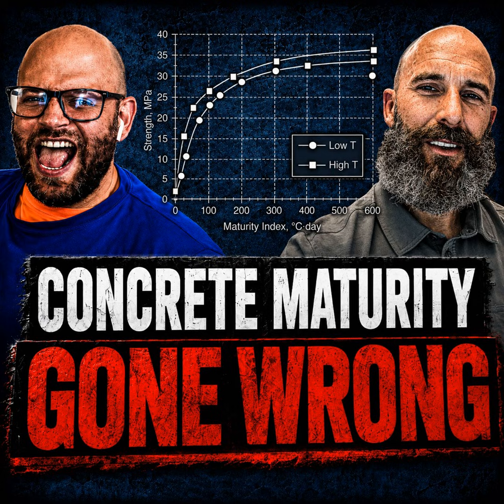So what does datum temperature mean? If I took that type 1 cement to a type 3, it's a faster setting cement. My datum temperature is lower, meaning because I'm using a finer cement that kicks off like a bat out of hell when I add water to it, it can set up in lower temperatures, or that maturity cycle can happen in lower temperatures. Now, if I'm using something like a type 2 cement, or a type 5? Or let's go to an oil well cement, the grain size is huge, they're coarse grains. It needs a higher datum temperature to start kicking off the activation energy, or the maturity process.